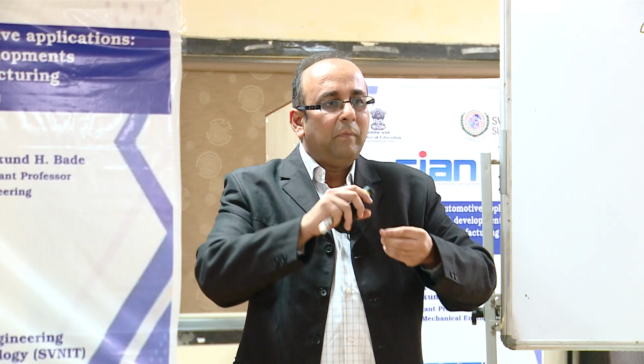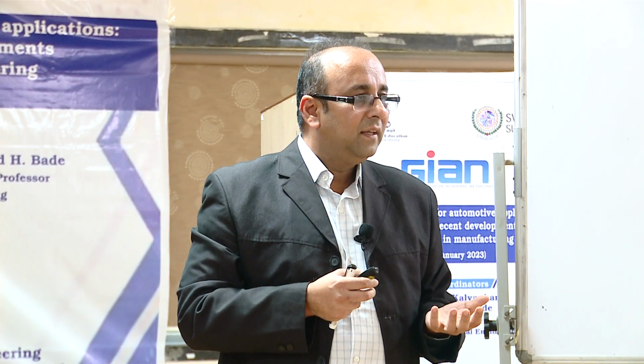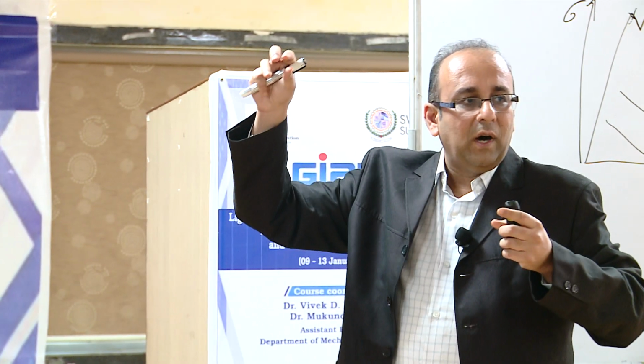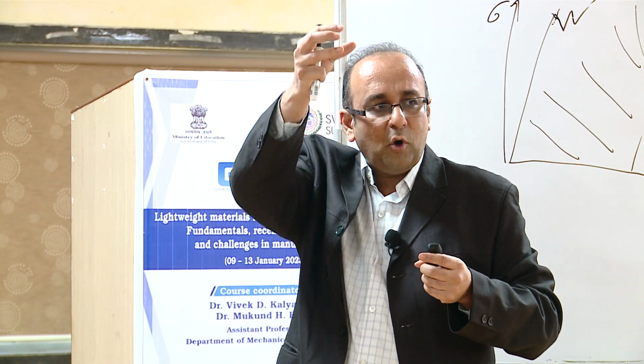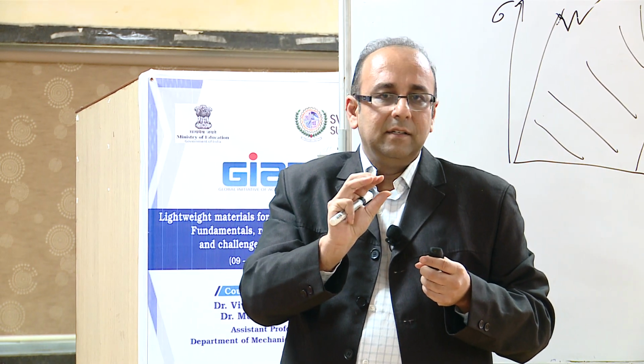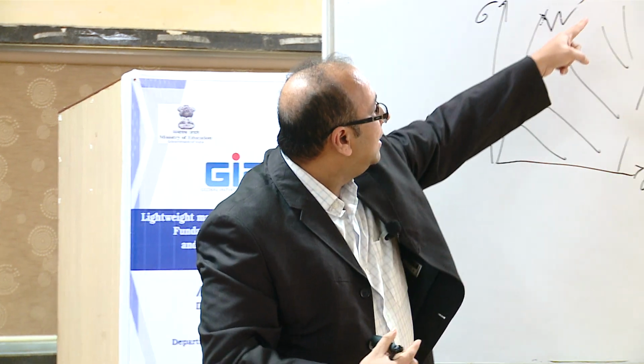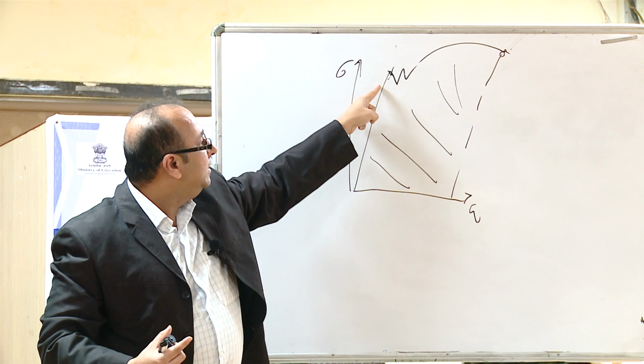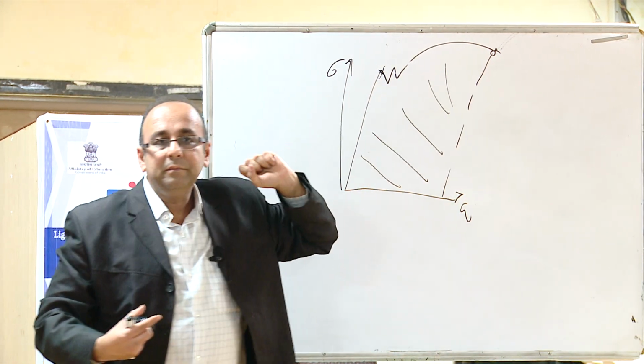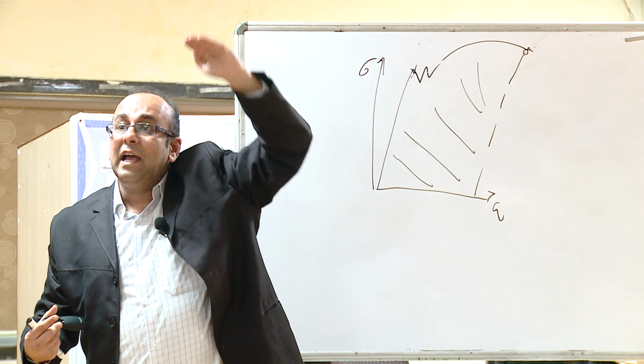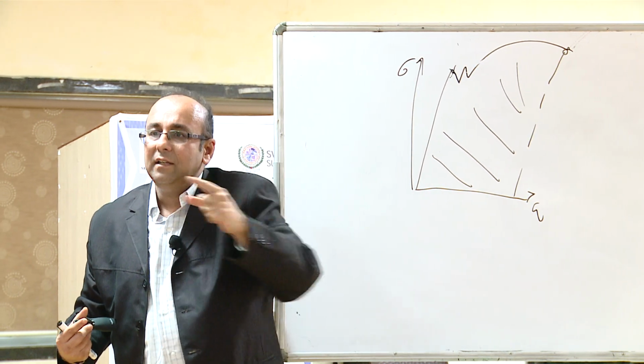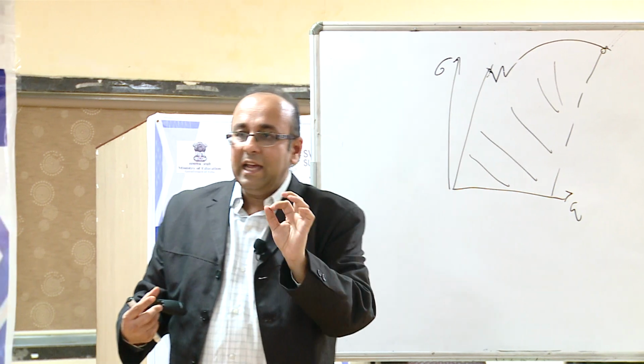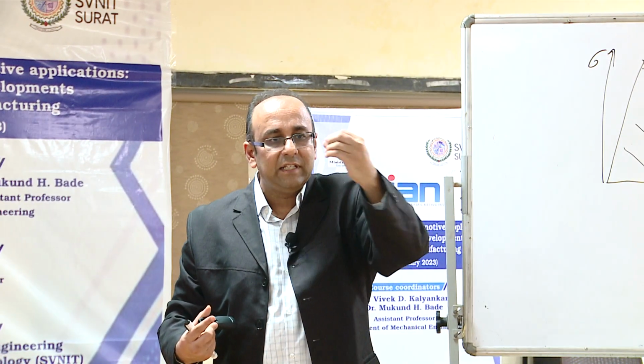So if I would combine some of these phases together, I would get the benefit of both of them. That's what is a dual phase material. You are combining ferrite and martensite. It means basically you are having ferrite, but at the same time some austenite is getting converted to martensite. It means I am getting higher elongation, higher strength, or a higher yield point and higher elongation. Maybe the strength is not that high as martensite, but still I am getting that same energy. My aim is to get this required energy available in whichever ways.